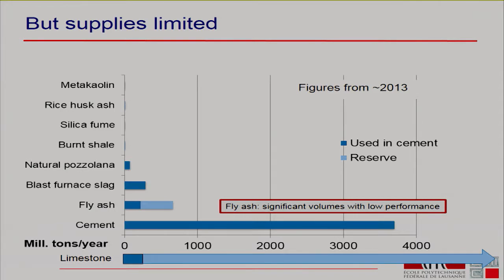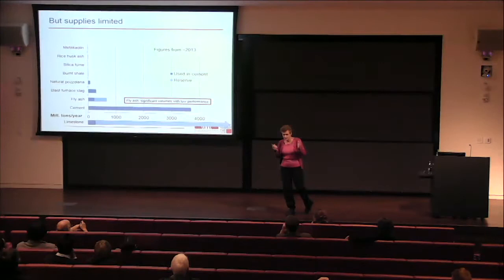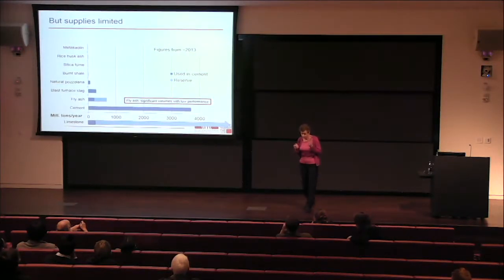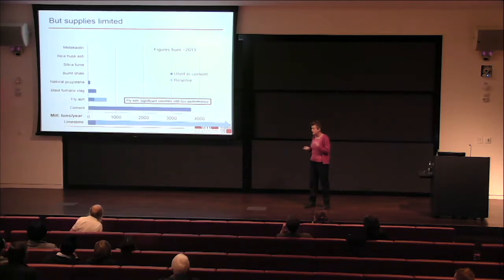So we take slag. I mean, slag is a great thing. You can mix it at 70% or even 90% substitution of clinker. But the amount we have worldwide is about 5% of the amount of cement we need. And 99% of that is already being used in concrete. So all the benefit of CO2 reduction from slag, we already have. We can't go any further with that because there's no more slag available.